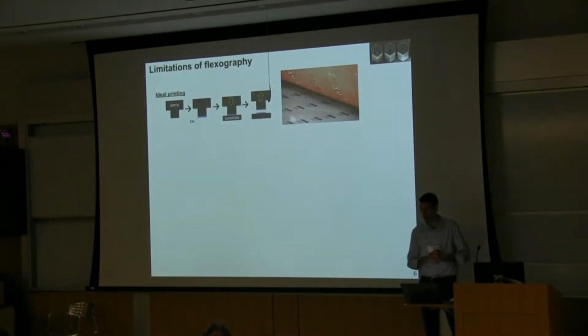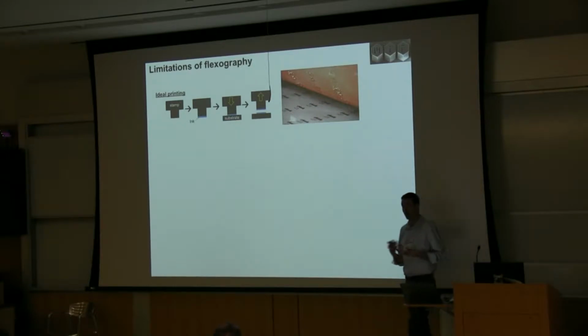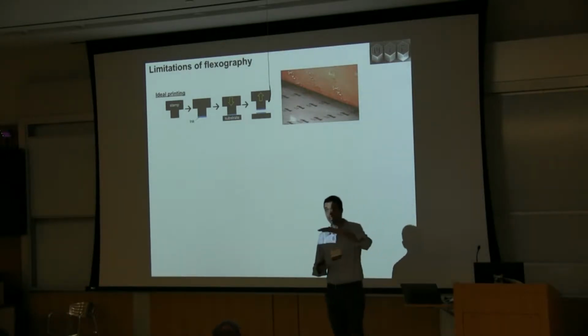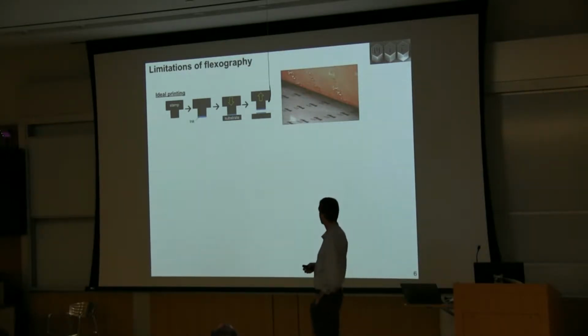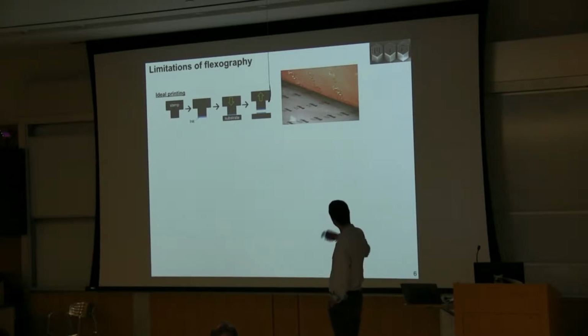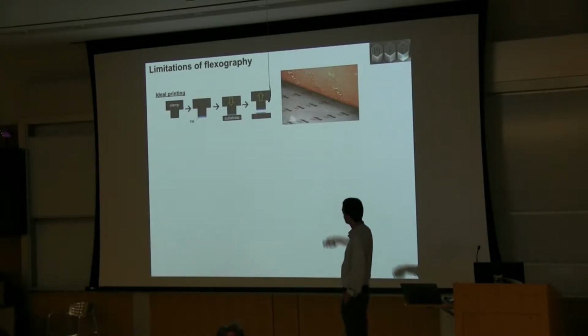So this has inspired our work to look into the limitations of flexography, the limitations of this simple contact printing process for ink transfer. And ideally, if I took a rubber stamp, say it's just one feature on a flat stamp, I would want to put a thin layer of ink on the raised feature of my stamp, contact the stamp with the substrate, and split it apart so I leave this perfect thin layer of ink on the substrate entirely, or I could split it evenly and then refresh.